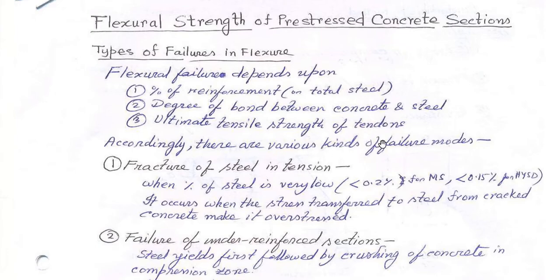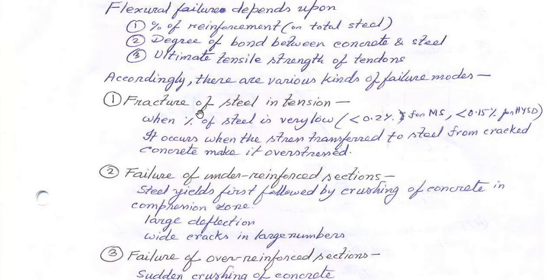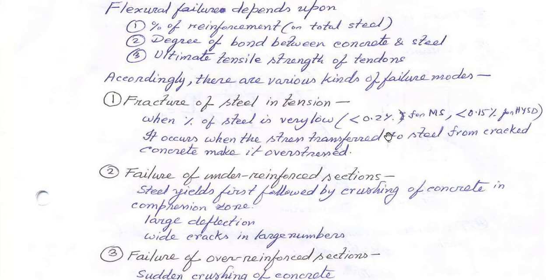There are various failure modes in flexure. The first is fracture of steel in tension — the steel gets elongated and fractures when the prestressing steel percentage is very low, less than 0.2% for mild steel and less than 0.15% for HYSD steel. This occurs when the stress transferred to the steel from cracked concrete causes overstress: once concrete cracks, the load is taken by the steel, and overstressing causes fracture of the steel in tension.